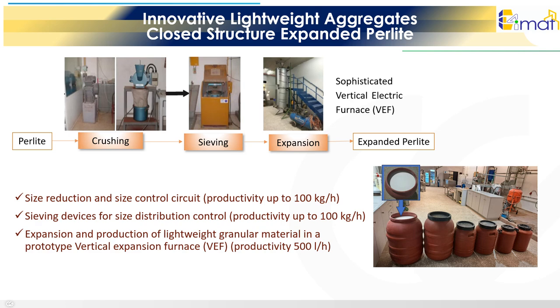By applying a carefully tuned thermal treatment and optimizing the feed characteristics, it is possible to engineer fillers with targeted size, porosity, sphericity, and density. The resulting closed structure perlite achieves significantly higher crushing resistance and lower open porosity compared to conventional expanded perlite, offering improved mechanical and thermal performance in the final mortar formulations.